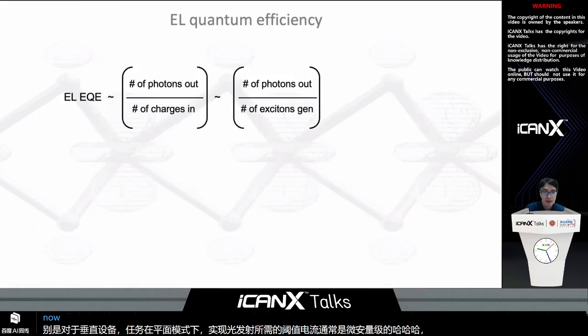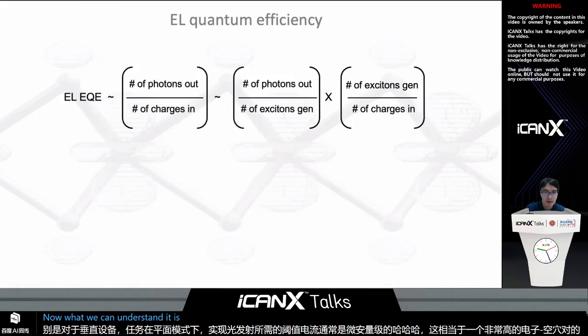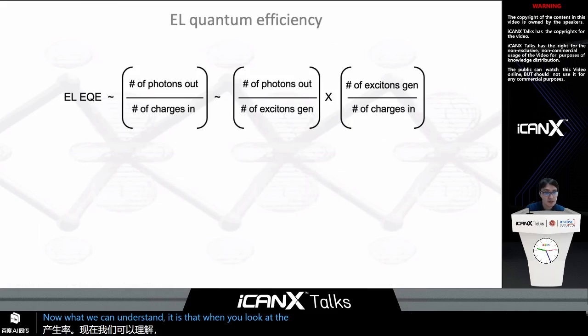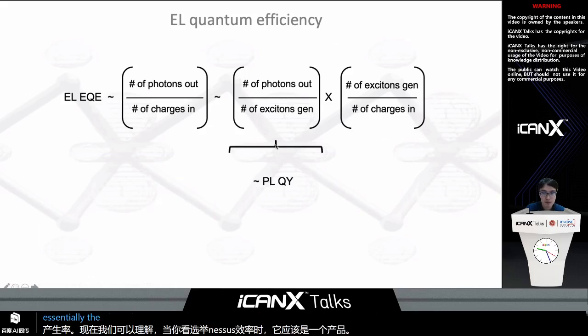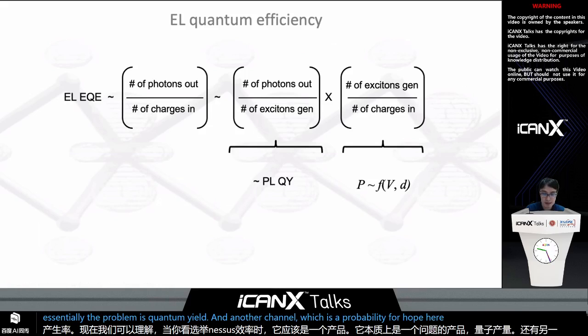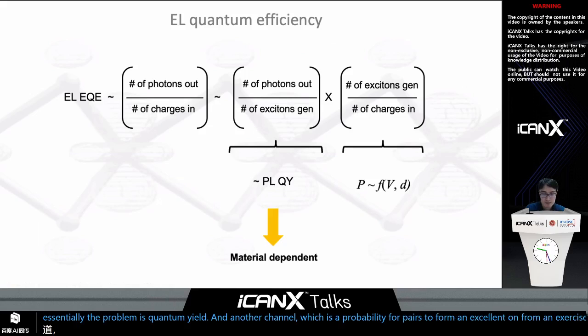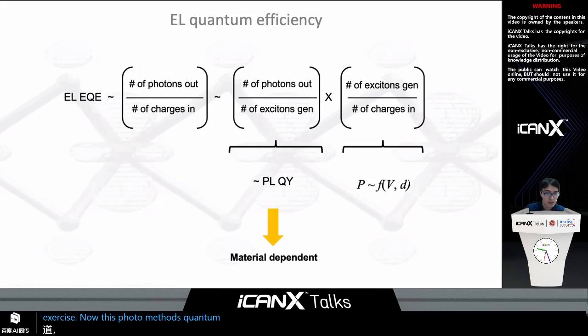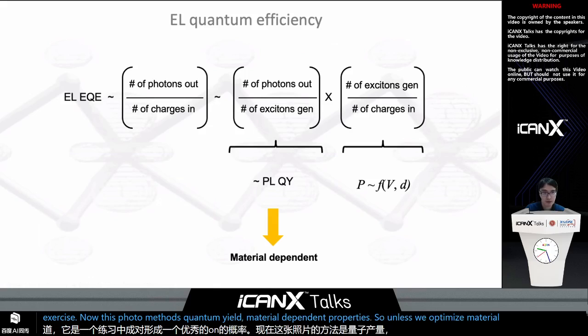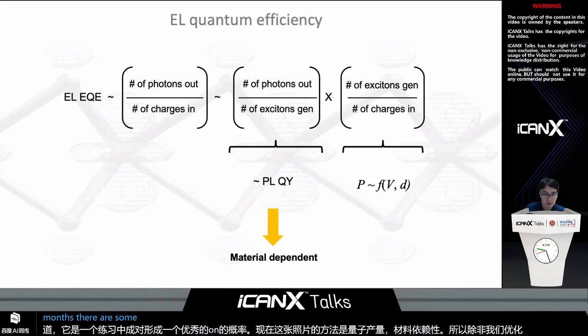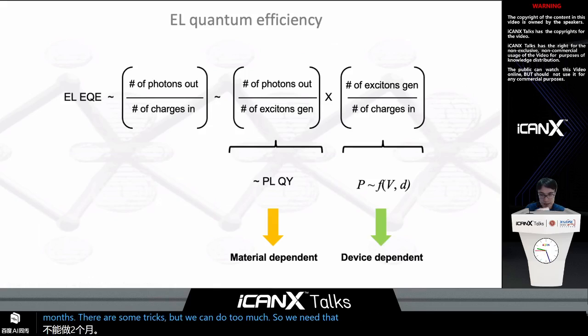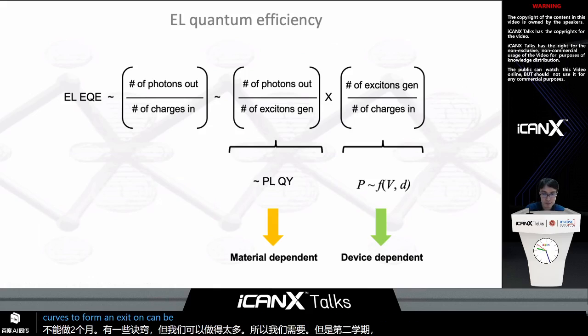Now, what we can understand is that when you look at the electroluminescence efficiency, it is a product of essentially the photoluminescence quantum yield, and another term, which is the probability for electron hole pairs to form an exciton. Now, this photoluminescence quantum yield is a material-dependent property. So unless we optimize the materials, we couldn't do too much. There are some tricks, but we leave that. But the second term, the probability for the electron hole pairs to form an exciton, can be tuned.